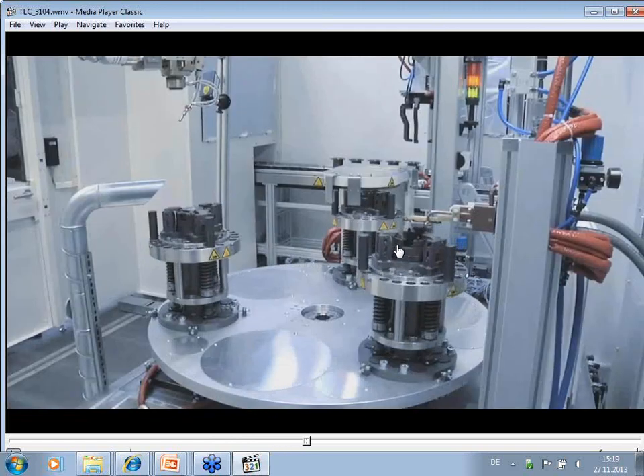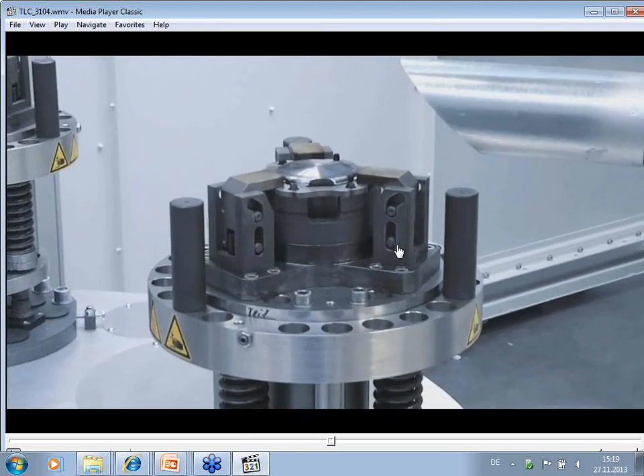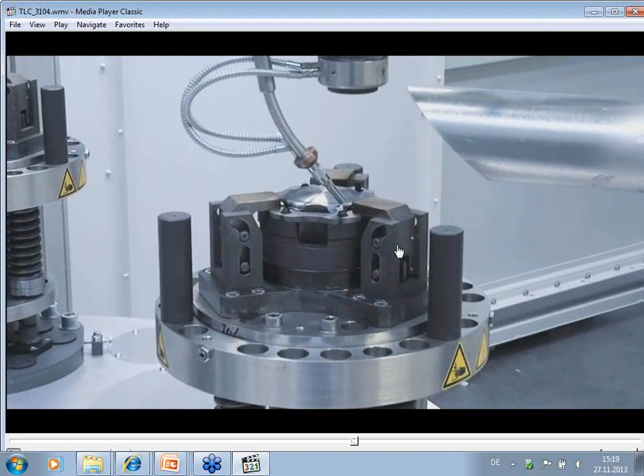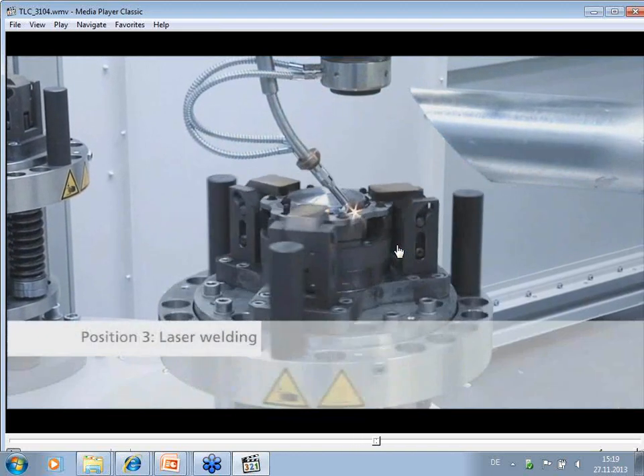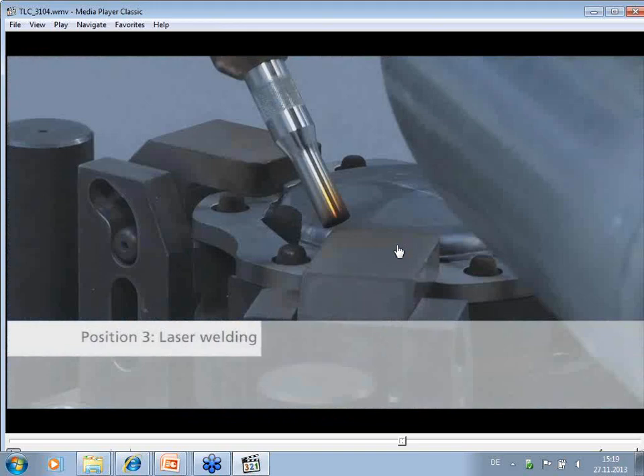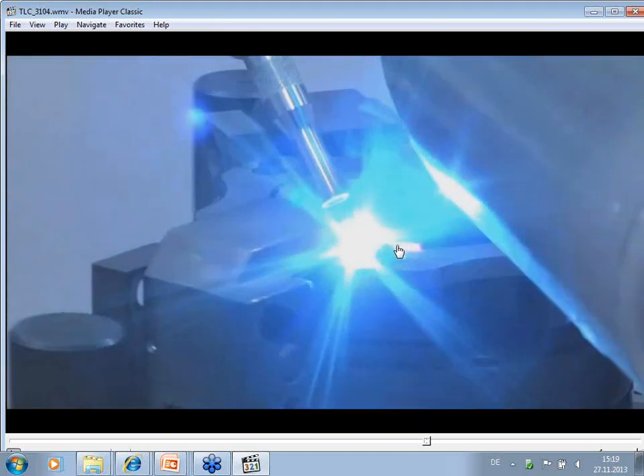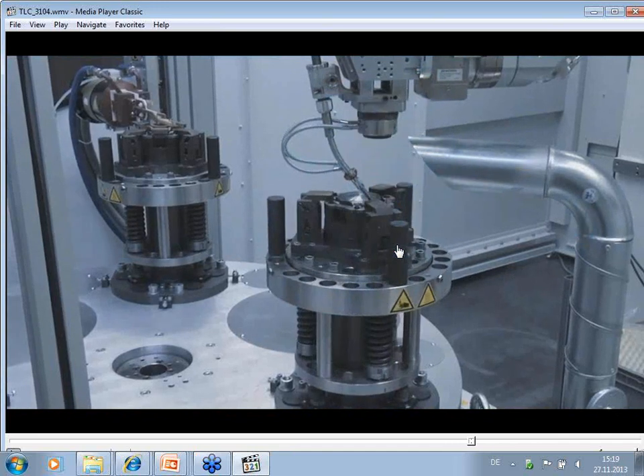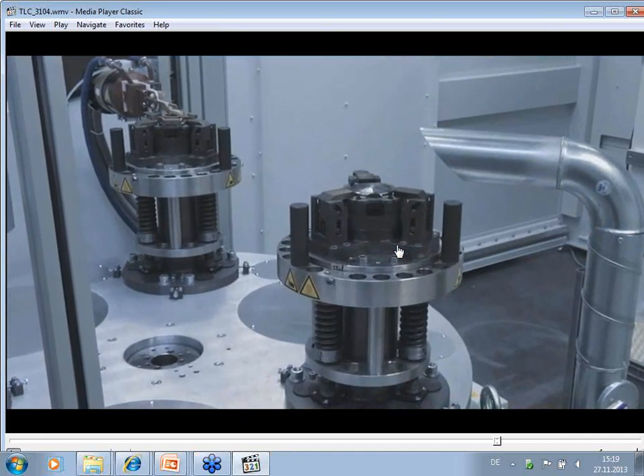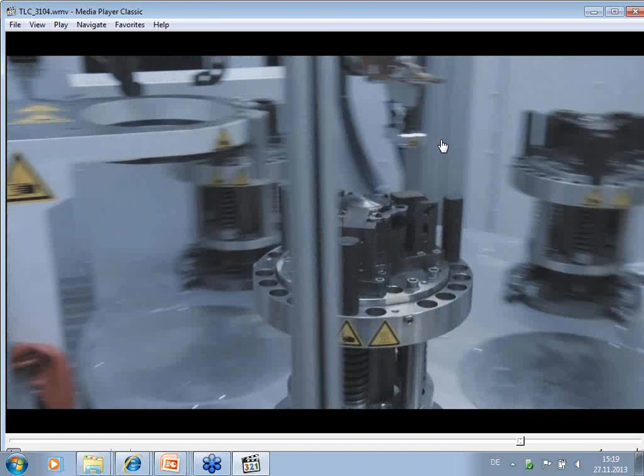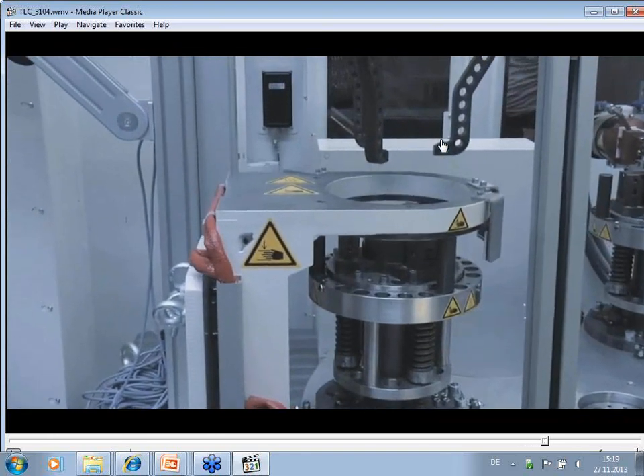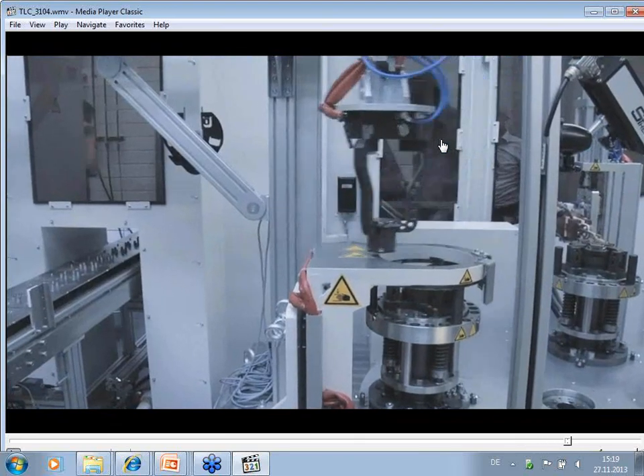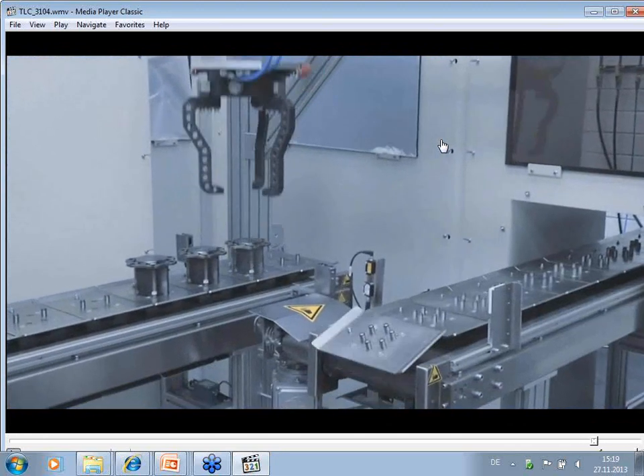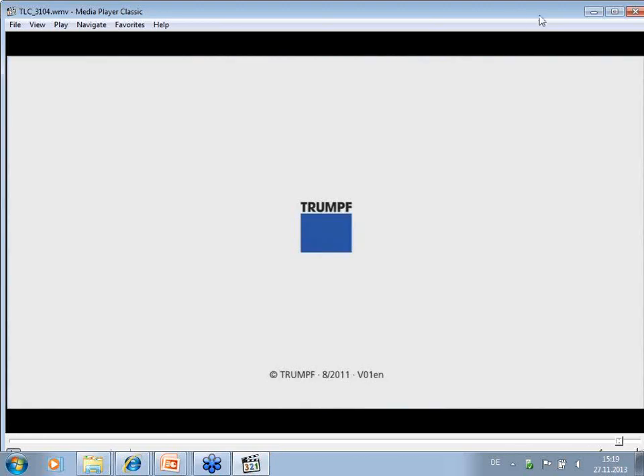You can see now the part here glowing a little bit. And the third step, as already mentioned, is the laser welding process, a deep welding process. In this example, it's about 5 to 6 millimeters deep penetration. The temperature with this induction preheating system before we start to weld is about 450 to 500 degrees centigrade. With this process, we are able to reduce the hardness, so that there's no or just a little bit of martensite inside the structure of the material. After the welding process, we bring it to the exit conveyor.